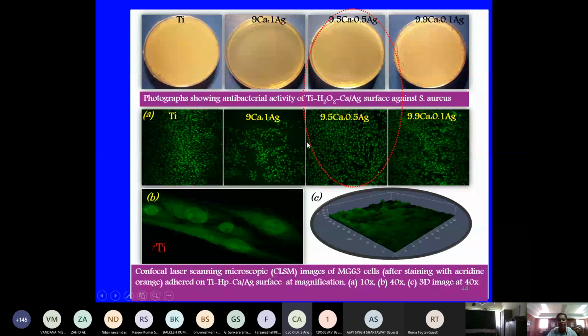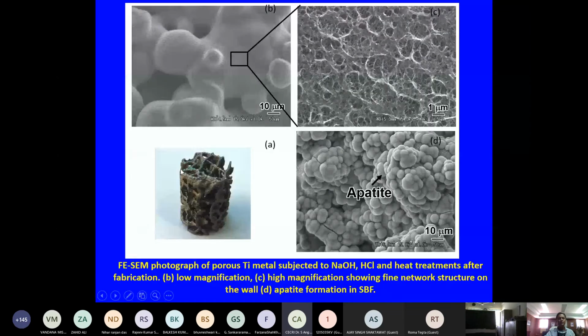And you can see the lower green color image where the bone cells, the live MG63 cells, are present on this optimized silver containing calcium modified titanium surface. And you can see this is basically a cancellous bone scaffold, and after this chemical treatment we have modified the entire surface including the pores also. And the advantage, since this is a liquid chemical treatment, is that it helps make this type of porous network structure even inside the pores,